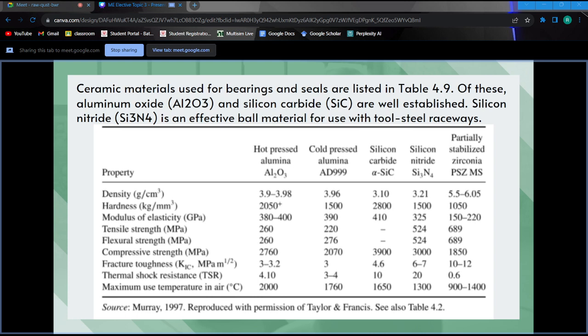to 3.98 gram per cubic centimeter, hardness na 2,050 kilogram per square millimeter, modulus elasticity po na 380 to 400 gigapascals, tensile strength at 260 megapascals, flexural strength at 260 megapascal, compressive strength, which is 2,760 megapascal, fracture toughness, 3 to 3.2 megapascals, and thermal shock resistance is 4.10.